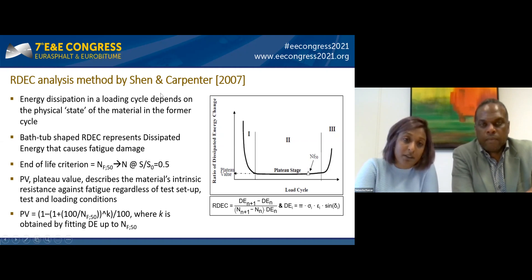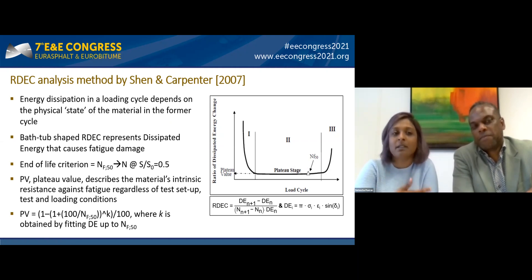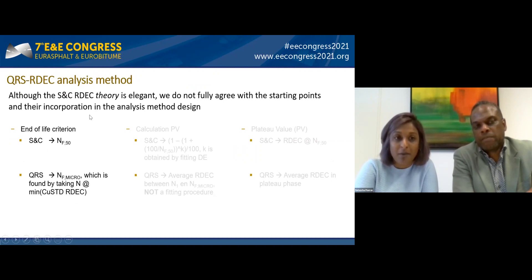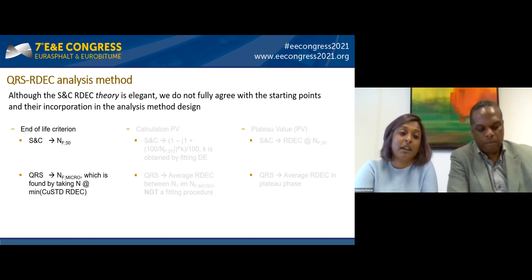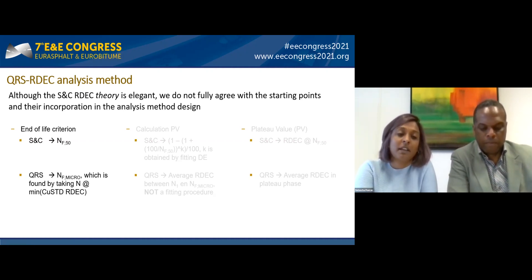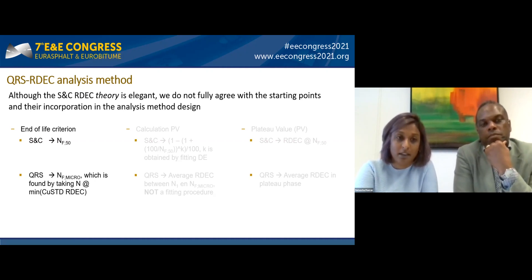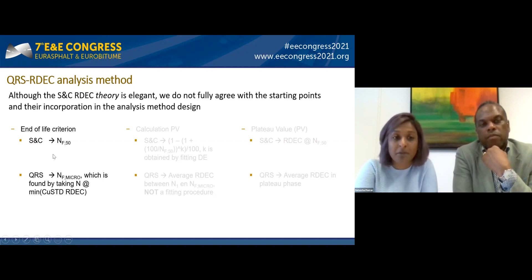Because of this logical starting point, we decided to apply this analysis method to DSR mortar fatigue test data. Although we find the theory elegant, we do not fully agree with some of Shen and Carpenter's starting points. The most important point we disagree with is the end-of-life criterion: Shen and Carpenter said it is the number of load repetitions at 50% stiffness reduction. When we tested the same mortar with only the type of polymer-modified bitumen changed, we found that the 50% stiffness reduction can occur in phase one, two, or three — making it not representative for end of fatigue life.